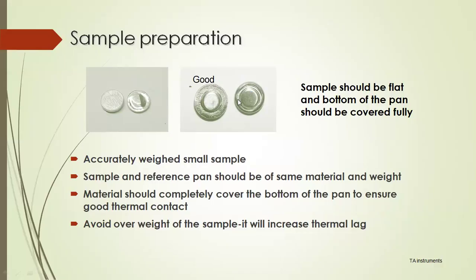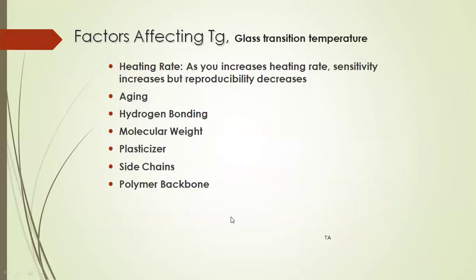Also frame your sample in such a way that it covers the whole base of your sample pan. It should not be curved or like this, because this will give me a thermal lag. So this is a good sample which is cleaned properly. My sample base is fully covered with my sample. Accurately weighed sample pans will give you more accurate results. And avoid overweight also, in DSC also, it will avoid the thermal lag.